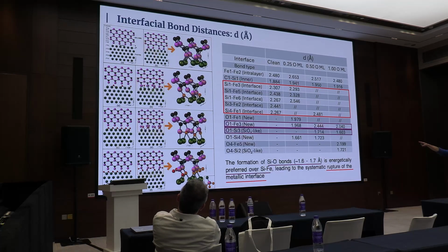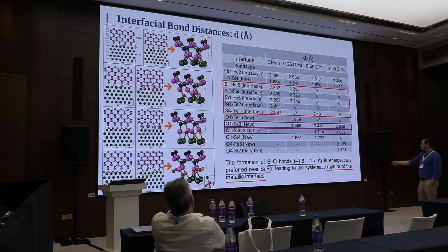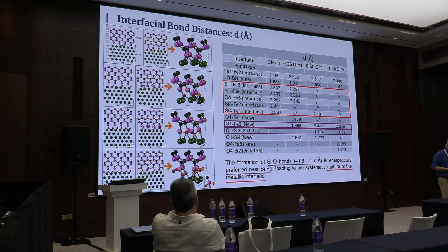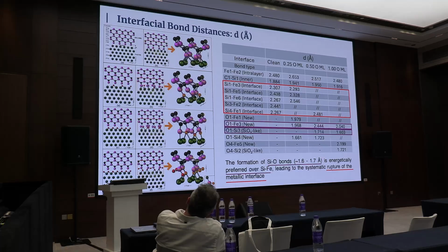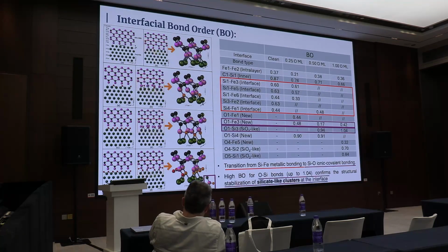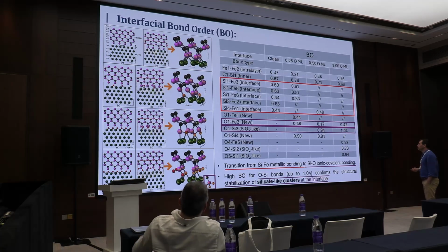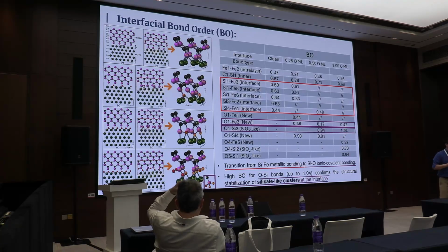We observe the same. For example, the oxygen-iron interaction is created, and we observe that the silicon-oxygen interaction is created, but the distances look like, as I say, a glassy connection. We will keep this in mind, but this could be an explanation of the situation, the type of bond that we are having, and what this implies. So let's study another parameter that we can use to measure how the connection between the atoms is. So bond order says something about the type of connection we have.